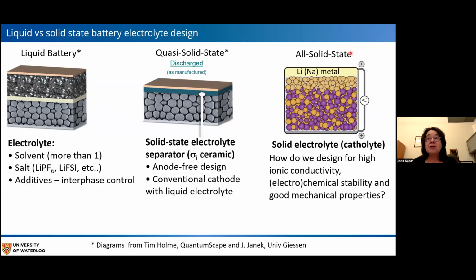In contrast, in an all-solid-state cell, as I said, there's no liquid. And so we have to worry about how to design for high ionic conductivity, electrochemical stability at the interfaces, and also worry about these mechanical properties that are necessary to really sustain the cell through the redox cycling and volume expansion contraction effects that we have.